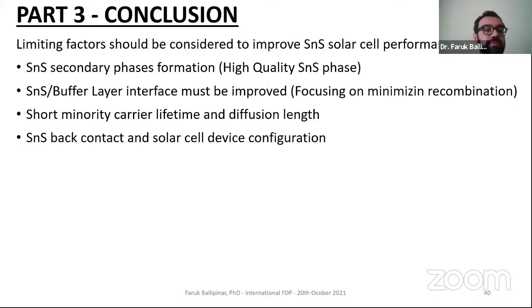But there are some problems that haven't been overcome yet. Tin sulfide secondary phases formation. We are getting the dominant tin sulfide phase, but secondary phases are still available. The other secondary phase is SnS2, and SnS2 is N-type. We basically want pure P-type. So this is a very big problem for sulfur-based materials.